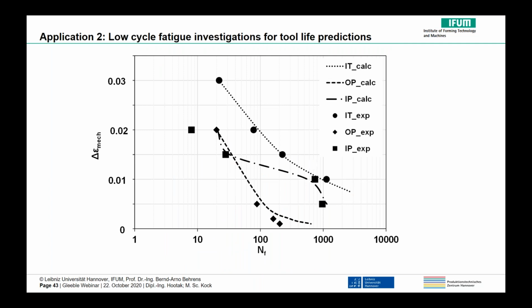The main purpose of the experiments in this work has been to determine the parameters of the tool life model for the tool material under investigation. Therefore, after the tests, the model equations were determined. Corresponding curves for the different cases of tests were calculated and displayed in the depicted figure. The comparison shows that the calculated curves can predict the cycle number fairly accurately. Subsequently, the total tool life model was implemented in Simufact Forming by means of the user subroutine.